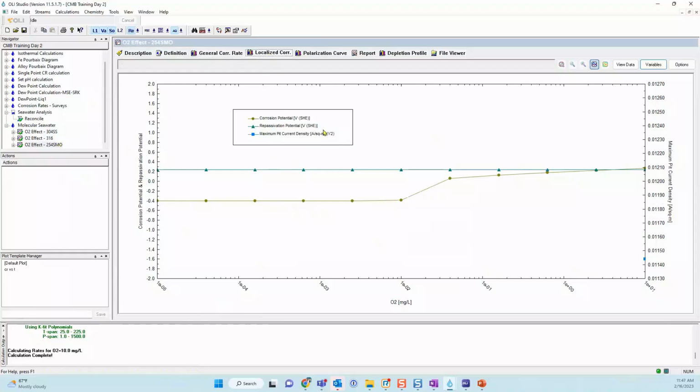So I would recommend using this alloy for seawater applications. It is susceptible to localized corrosion a little bit, as you will see here to the right, right? The penetration depth would not be that much, 0.01 millimeters in this case.